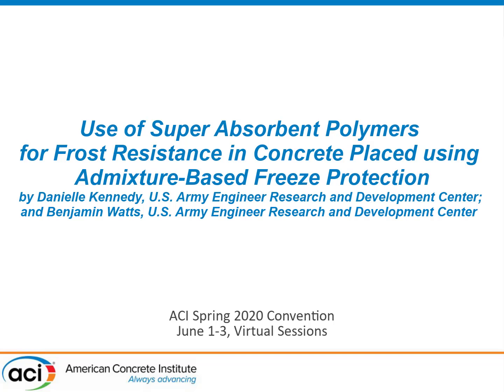We tried 4 different dosages, which I'll go back and say, and these are all based on the volume of the concrete as well. So the dosages we tried were 7.5 milliliters per gram, all the way up to 45 milliliters per gram. And the equivalent concrete dosage to that is about 14 pounds per cubic yard for the lower end, and about 2.25 pounds per cubic yard on the higher end.